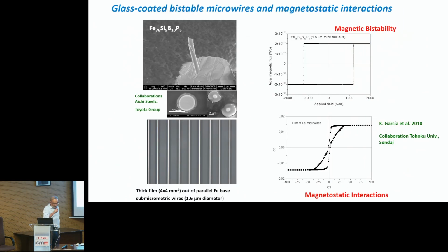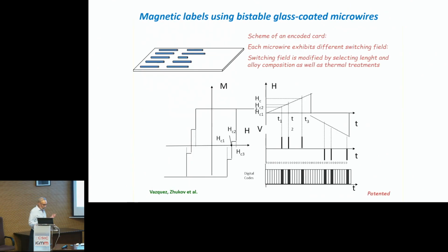Now I would like to give some examples of applications with these microwires. This microwire has a magnetic bistability with a square behavior. But if we are able to distribute a number of microwires nearly parallel to each other, in a planar arrangement, so the wires are really parallel, you see that the response is completely different. It is completely different because of these magnetostatic interactions. So these interactions are very important to control the magnetic response of a set of microwires. This enabled us to develop a patent for an encoded magnetic card with a number of different wires, each one having a different switching field. So we have some kind of digital code depending on the distribution of magnetic wires.